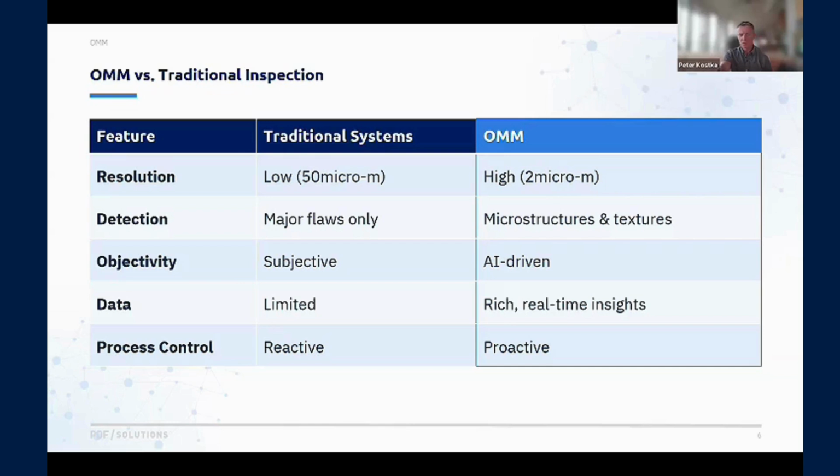And that in itself gives you two other things. That means we will see features every time we take an image. And those features are actual real things, where they're objective rather is maybe a better way of putting it, right? So NMC is a really easy example to talk about. In NMC, we can observe basically every single grain in every image, every single void in every single image, and we can quantify the size distribution again in every single image of those two features.